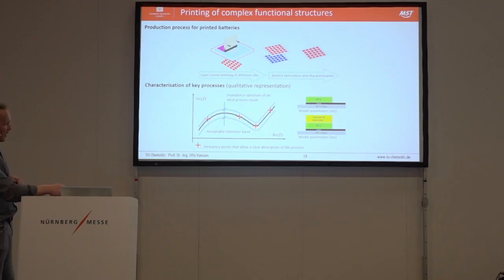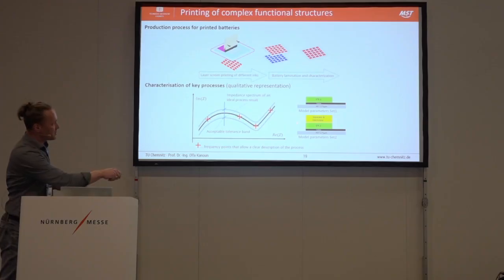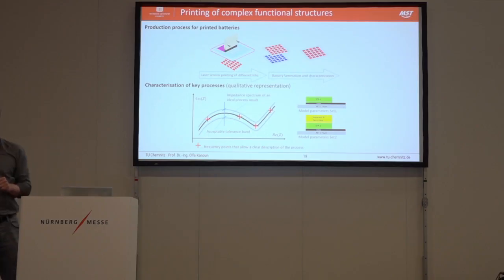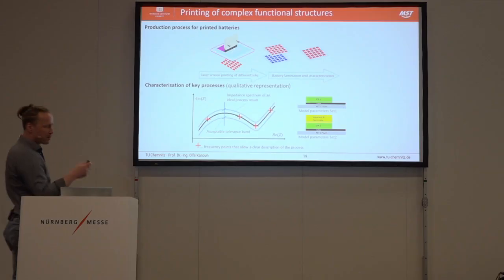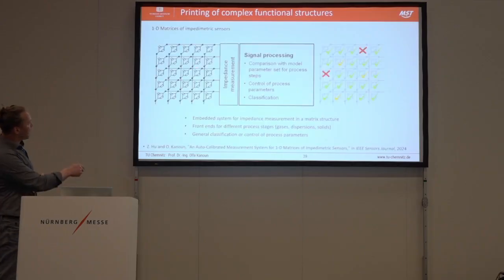Then we have the second printing step. This is this yellow layer. What do we need? Nothing else. We have, again, our capacitive structure. The only change is in the microcontroller, the model. Other model parameters for the double layer system. And also here, we have the ideal example, the golden sample from our lab, and we compare it with the result. At the end, we have a matrix analysis.